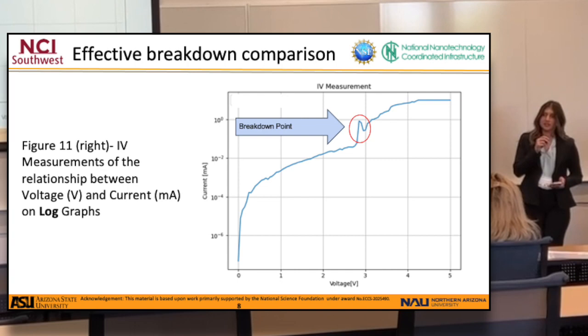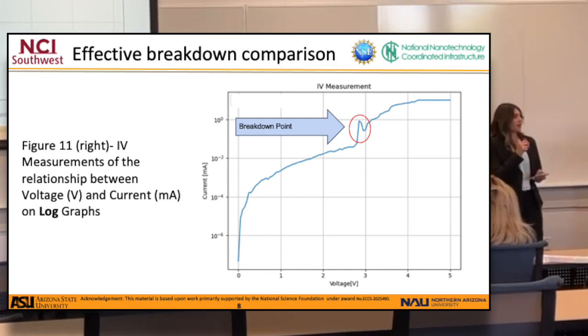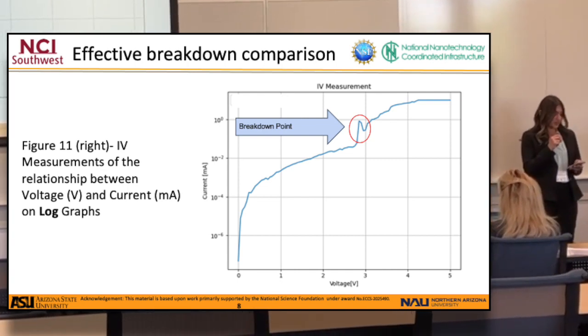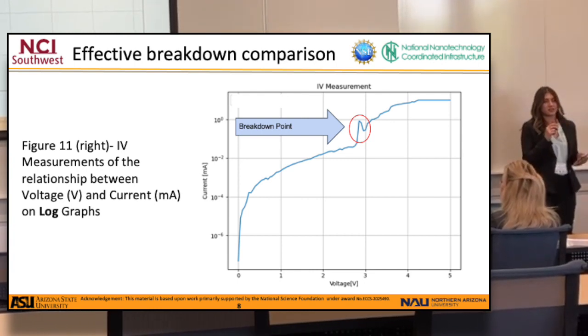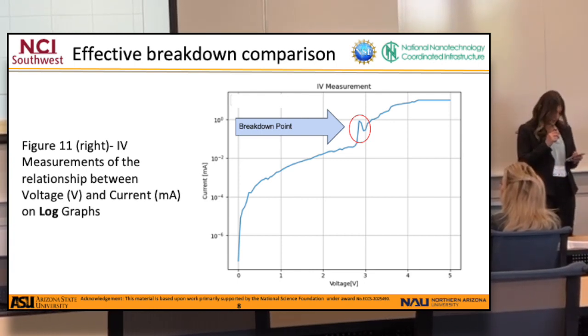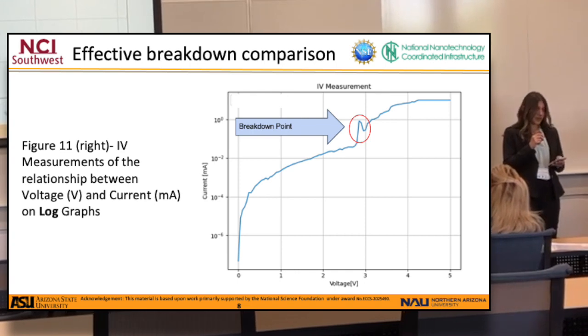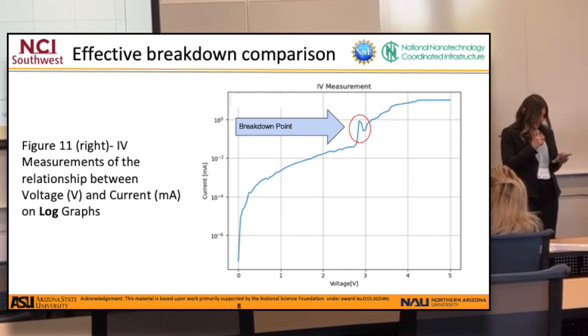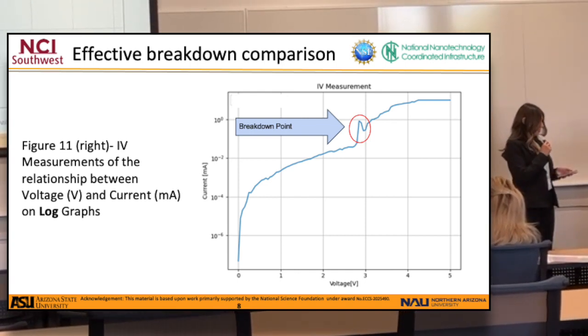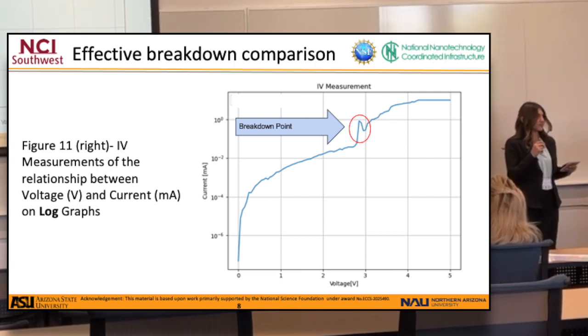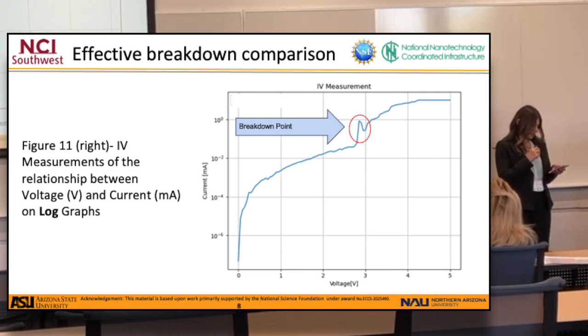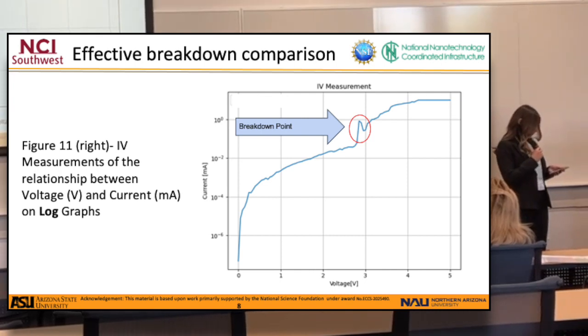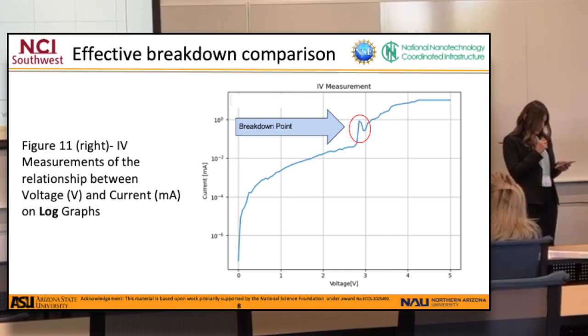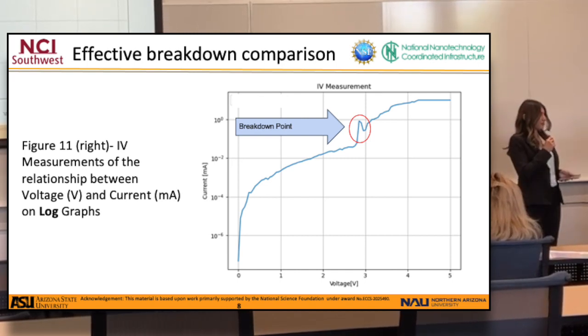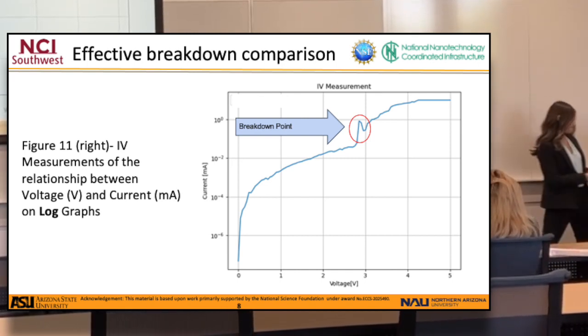We would also like to understand the benefit of analyzing the log graph as well, because we can observe the smaller details that don't seem as apparent in the linear graphs. Sometimes it's difficult to specify where breakdown occurs exactly, but since this graph is shown in smaller increments, it's more obvious to us. We can also observe the relationship between voltage and current is not exactly at 0 right before the breakdown occurs. It slightly increases before we see that large break.